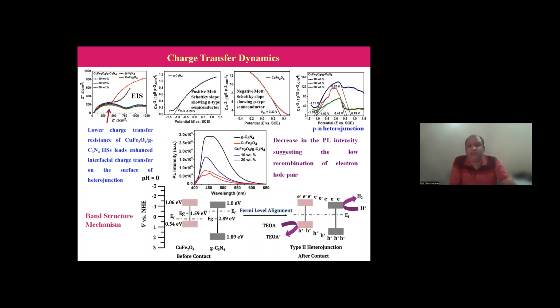And if you look at the band structure mechanism, before mixing the copper ferrite with the graphitic carbon nitride, the band positions of the copper ferrite and the graphitic carbon nitride in terms of the valence band and the conduction band are different. And when you mix both of them, there is Fermi level alignment. During the Fermi level alignment, the electrons present in the conduction band of the copper ferrite nanoparticles tunnel towards the lower conduction band of the graphitic carbon nitride, whereas the holes from the valence band of the graphitic carbon nitride tunnel towards the valence band of the copper ferrite nanoparticle. This type of charge transfer suggests type 2 heterojunction formation for the copper ferrite with the graphitic carbon nitride heterostructure.